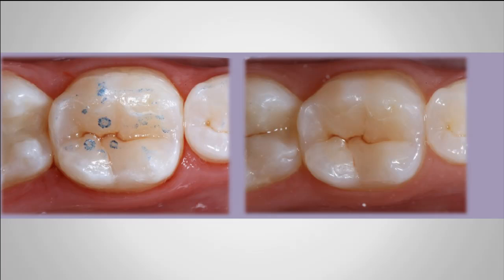This means gap. So usually this problem is generated by the adjustment. We use too much adjustment using diamond burrs, and we should use more carbide burrs. I'm going to show you the carbide burr that we use. But in this case, I had this problem after the adjustment. I can see this white line when I'm doing the adjustment. That means gap formation. This is the cause of this post-op sensitivity.